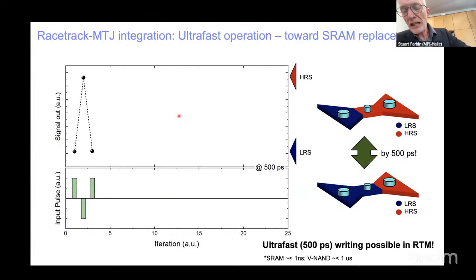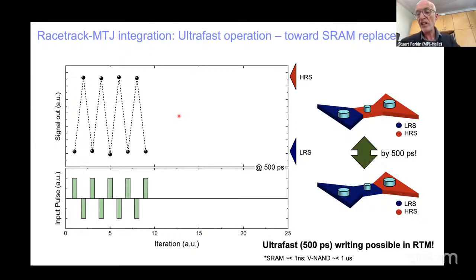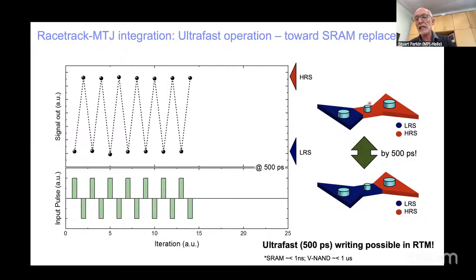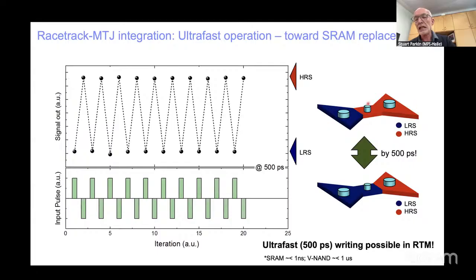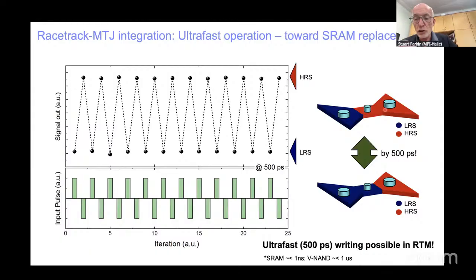And recently, we've also demonstrated we can integrate a tunnel junction device into a racetrack. And as shown on the right-hand side, here is a schematic cartoon of a 100 nanometer long racetrack with two electrodes to left and right. And there's three tunnel junctions. The only one in the middle is of interest. And as the domain is moved from the left to the right by a current pulse, which is only 500 picoseconds long, we can detect the position by the resistive state of this tunnel junction, which varies from a high to a low value.